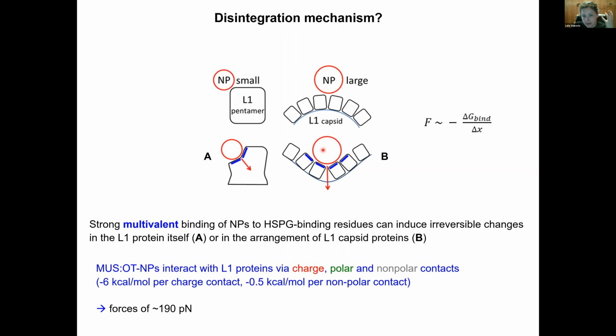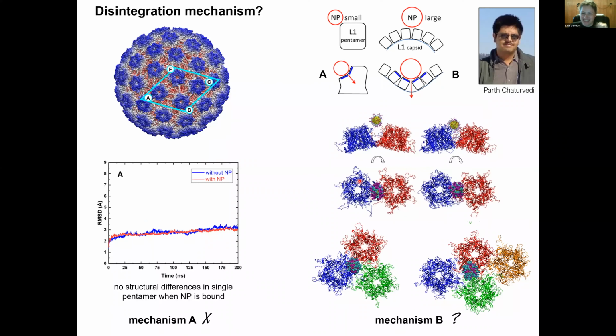The second mechanism would be that a nanoparticle binds to that capsid surface, which we saw how it looked like, and then it starts distorting the capsid proteins, their contacts, their junctions, and in that way destroys the virus. So nanoparticles could be acting with mechanism A, distorting single proteins, or distorting full capsids while keeping the viral proteins intact. Those were the 2 mechanisms which we then tested in simulations. And that's where a lot of the time went, because these are pretty big systems. So we first looked at mechanism A.